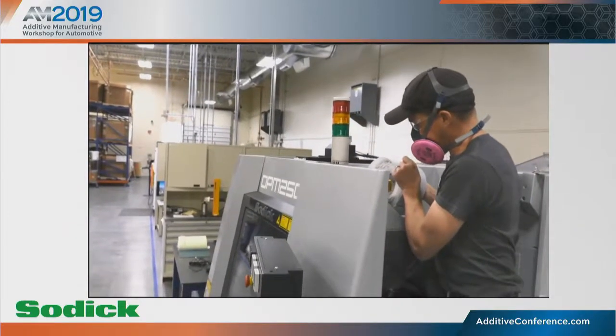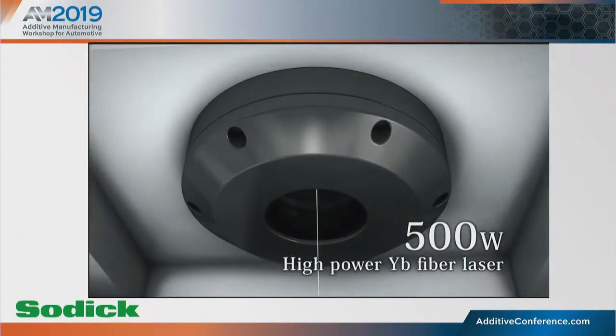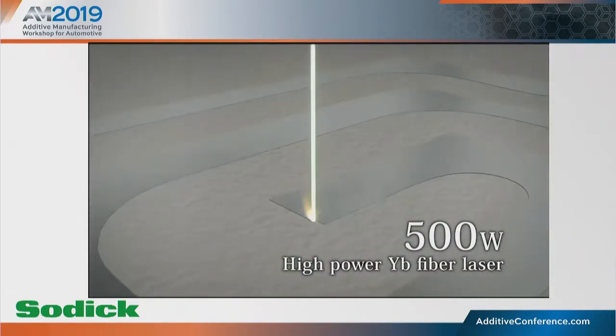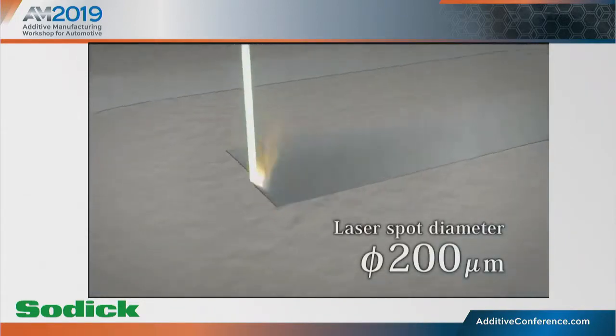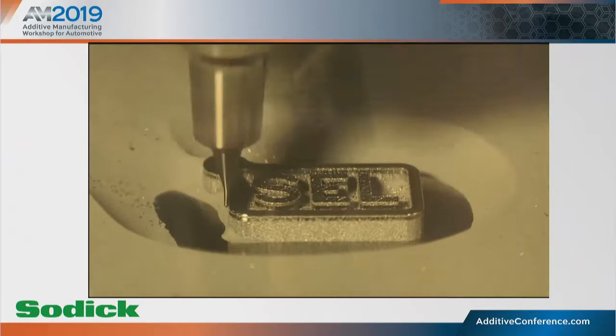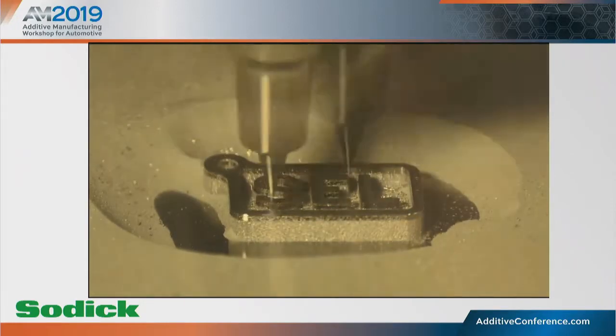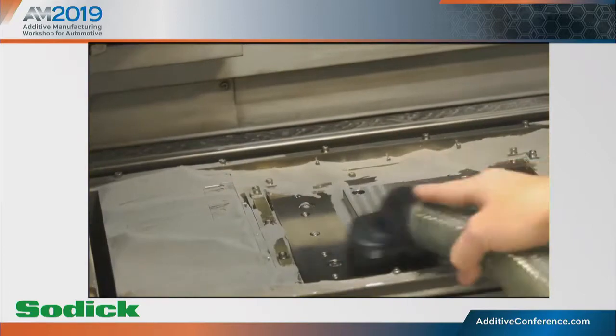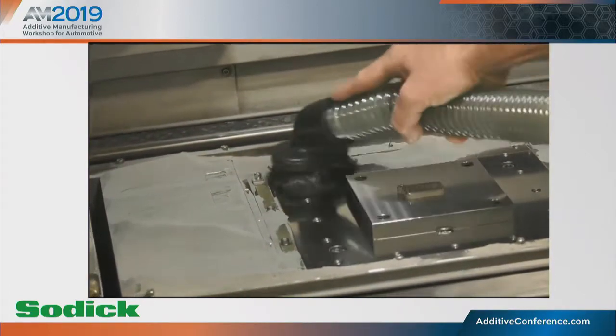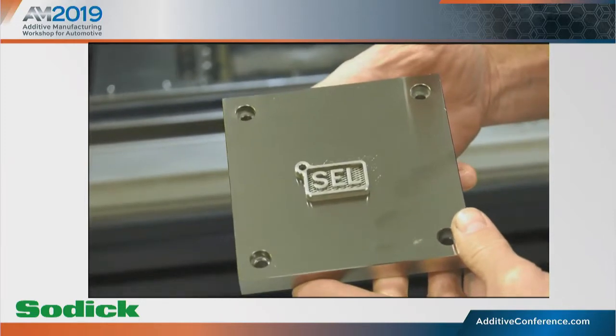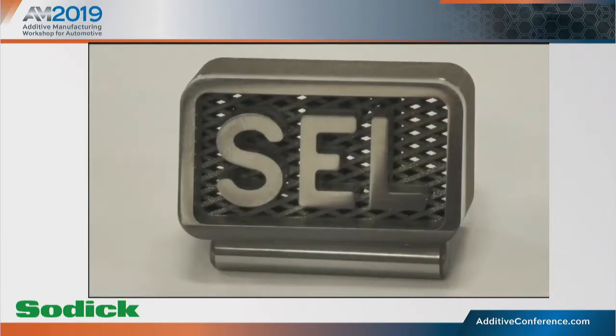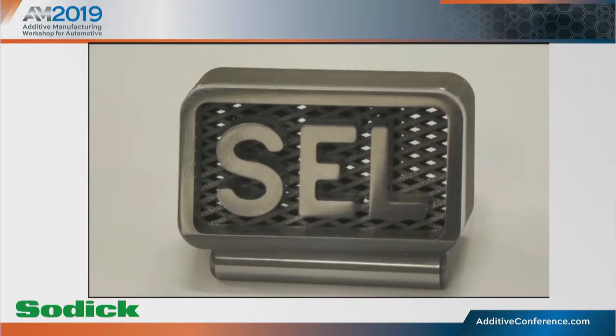In order to get a better idea of what that process looks like, it sometimes helps to actually see it in action. So you can see they're filling that raw material, that very fine-grained powder, into the build chamber. This simulation is just showing what the laser process would look like. But here you can see the final layer being sintered as well as machined in process to produce your finished part. So after evacuating your chamber, what you ultimately end up with is a solid piece, which in this example is essentially a trinket or a test part. But those hollow spaces could easily be conformal cooling channels, detailed surfaces, anything that you'd need it to be.